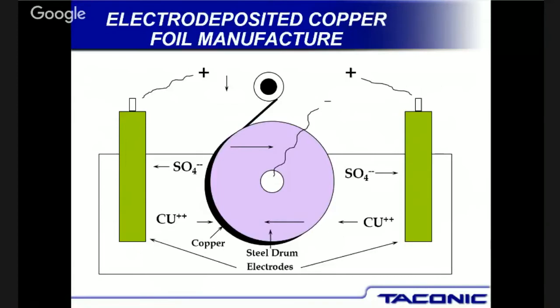Traditionally, there have only been two coppers available, rolled or standard electrodeposited. And ED copper, if you can imagine, the grain structure is perpendicular to the panel. So it's not good for dynamic bending. You can't crease it a lot, it'll crack.